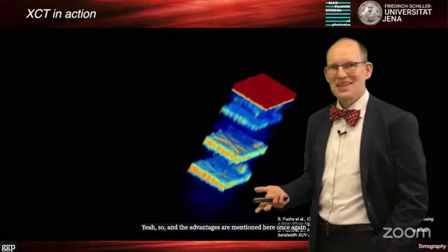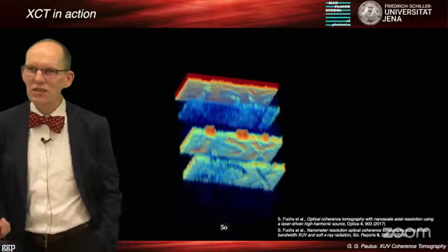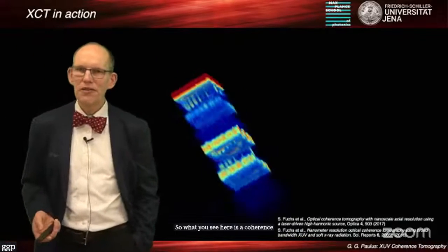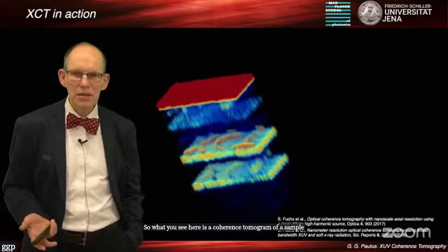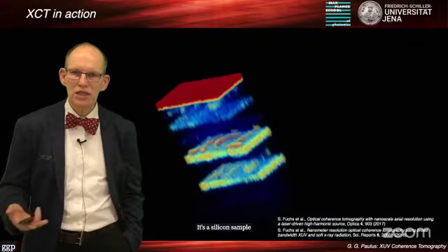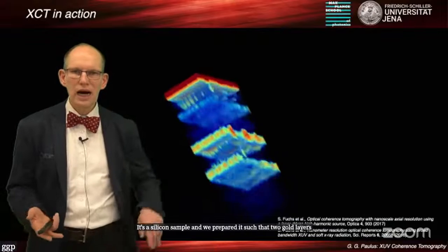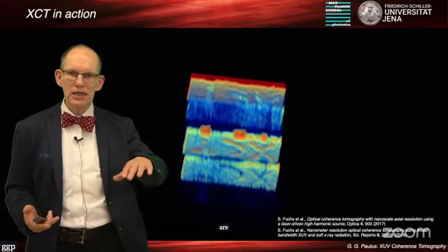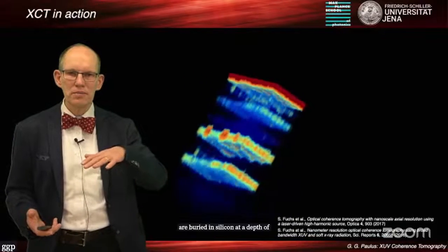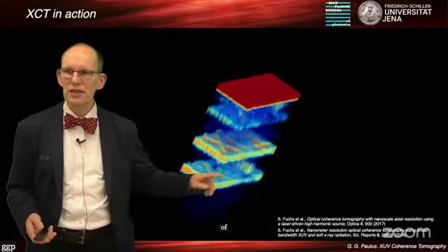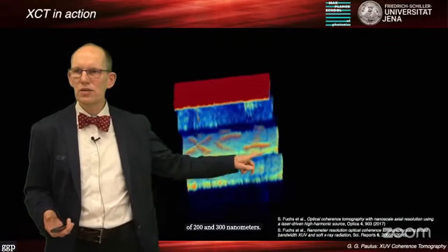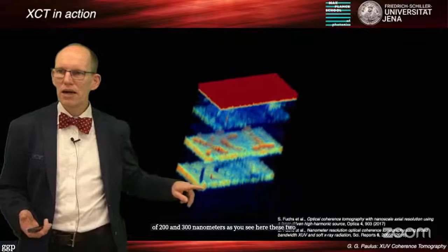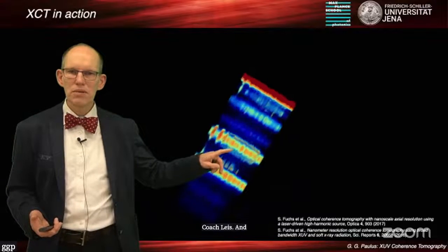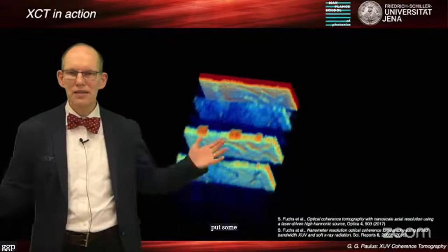Now, XCT in action. What you see here is a coherence tomogram of a sample. It's a silicon sample, and we prepared it such that two gold layers are buried in silicon at a depth of 200 and 300 nanometers. You see here these two gold layers, and we even put some letters on it, XCT by chance.